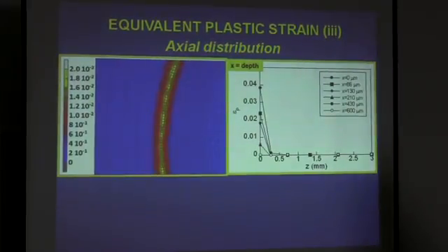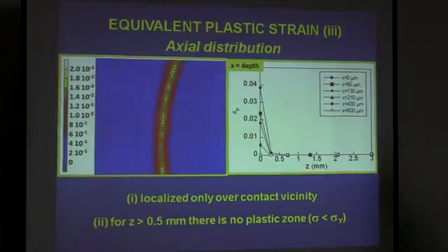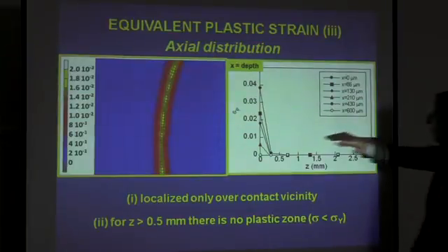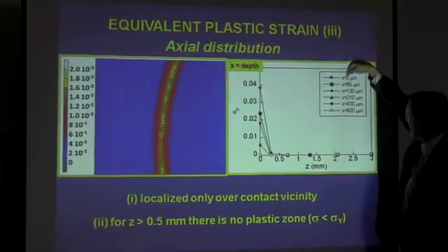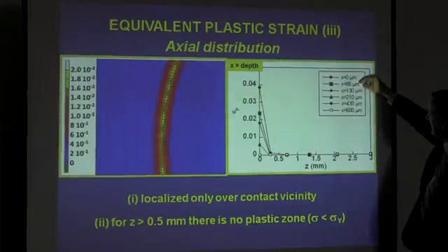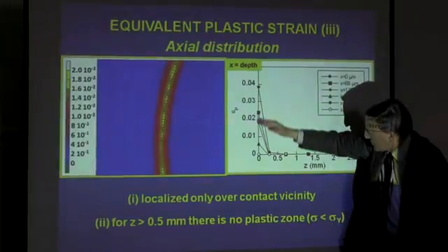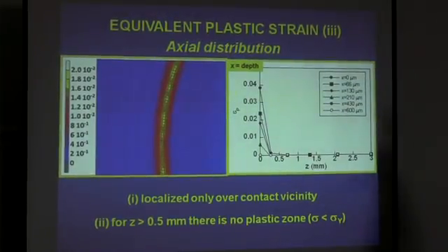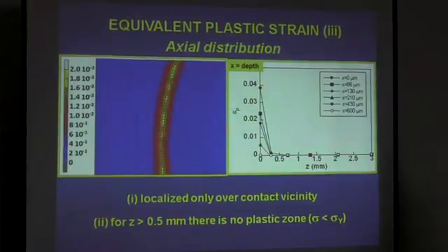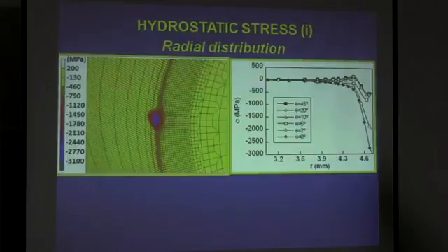With regard to the axial distribution of equivalent plastic strain, of course, localized only over contact vicinity, and for axial distance higher than half millimeter, there is no plastic zone. As the height increases, the distribution vanishes, separates from the contact plane, from the contact area in axial distance.